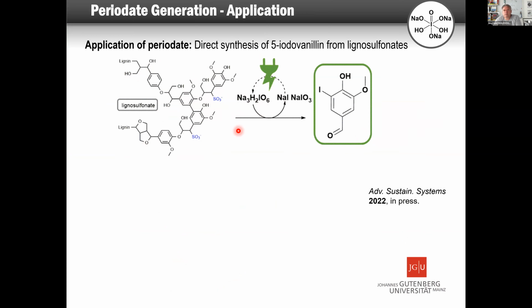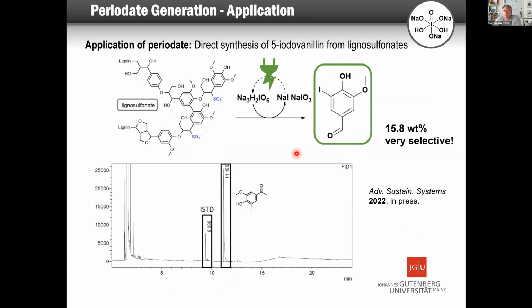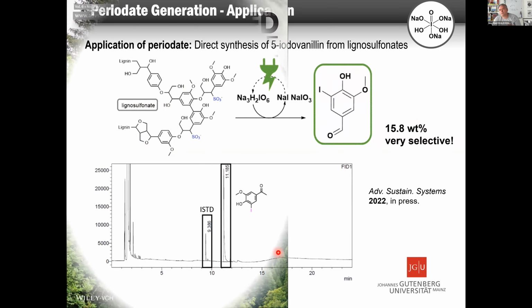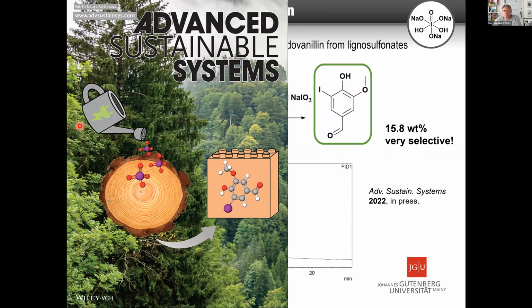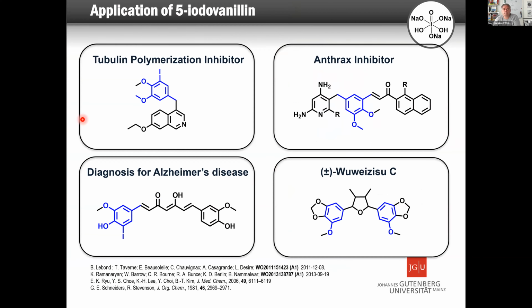And it turns out that you get here a relatively large amount of iodovanillin out of it, which is a very advanced building block. And you get more than 15 weight % out of the starting material. And you see the selectivity is quite outstanding. Therefore, we have made from wood, more or less directly, a building block which can be used for API synthesis and more advanced compounds. This is used for making tubulin inhibitors, anthrax inhibitors.